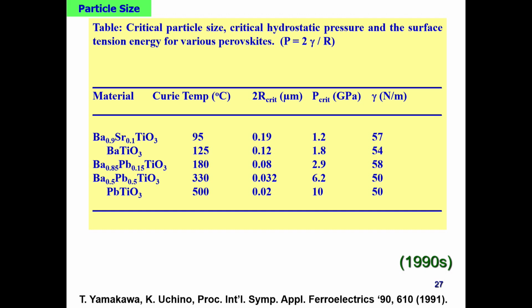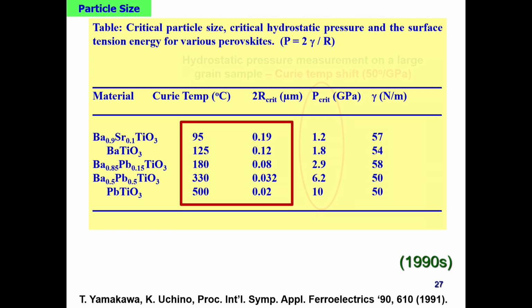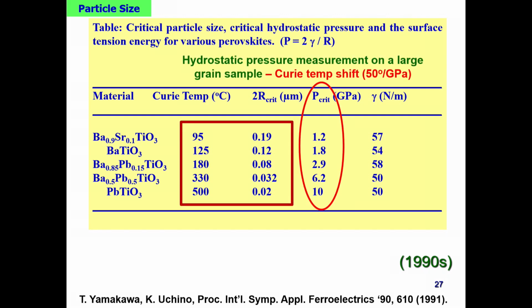we need to make smaller particles, because, as you are familiar with, the Curie temperature shift under hydrostatic pressure is about 50 degrees C per 1 gigapascal. So a large internal stress, a hydrostatic pressure, to reduce 500 degrees down to room temperature, is quite large; high pressure is required. So by taking this, we considered a proportional parameter: hydrostatic pressure is inversely proportional to the radius, okay? So gamma is beautifully around 50, plus or minus less than 10%, for any kind of ferroelectric material. So that is the 1990s.